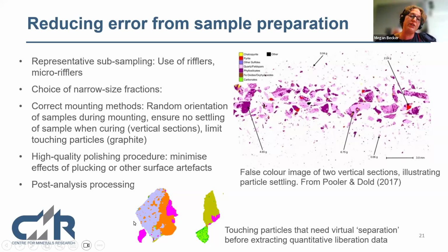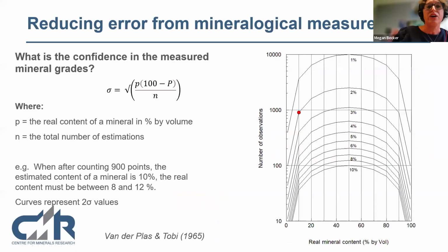So something like here, you've got 2 particles, pink, and this big one here. You can see that that is just stuck to the side of it. It's not a primary texture. And again, that one's sitting there. So we have measures that we use in sample prep to try and minimize this effect, but we also use post-analysis processing, and we tell the software to virtually separate those. So make that into 2 particles. And if we do any liberation or association or any form of textural measurement on something like this, chances are we're going to get the data wrong.